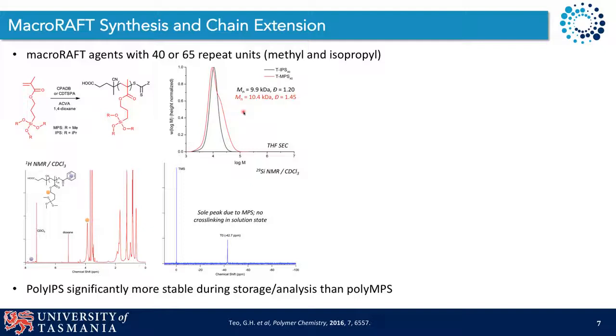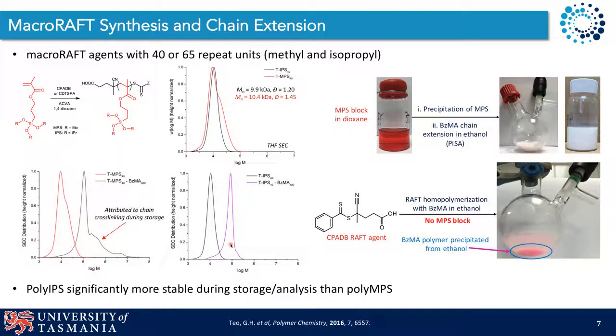It's important to point out that in solution, these polymers survive the polymerization process. The silicon NMR is very instructive in this sense. We get a single peak due to the trimethoxysilyl group in the case of MPS polymerization, indicating there's been no intra or intermolecular cross-linking during the polymerization process. When we perform our chain extension with typically 400 units of benzyl methacrylate, we see a nice clean shift in the case of our isopropyl stabilized system. The trimethoxy stabilized system gives a nice clean primary peak, but there is some higher order material, which we can attribute to chain cross-linking during storage.